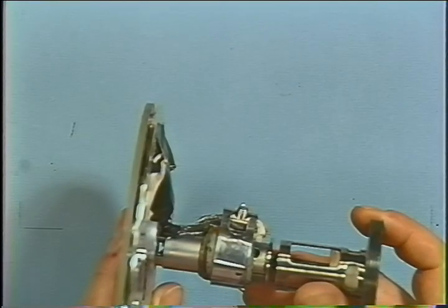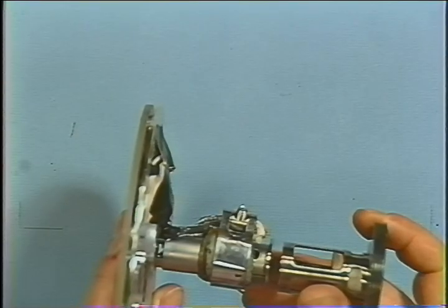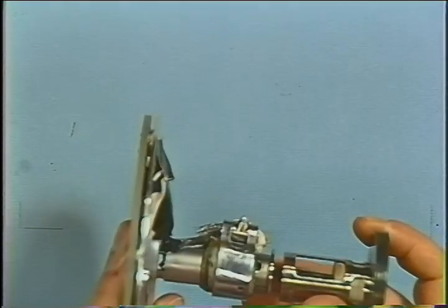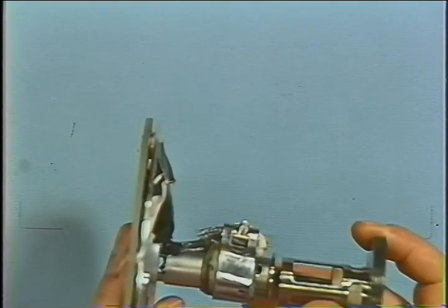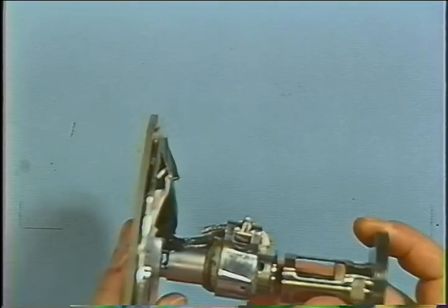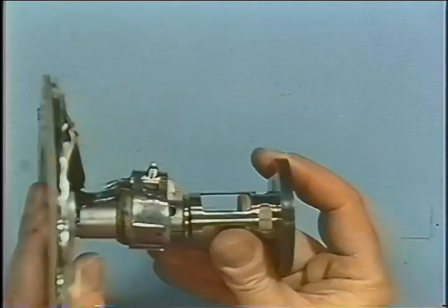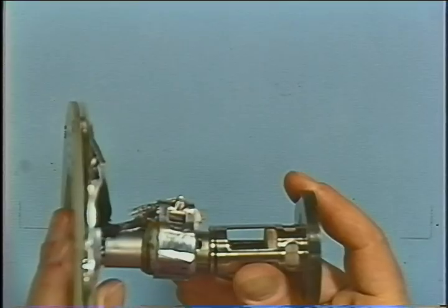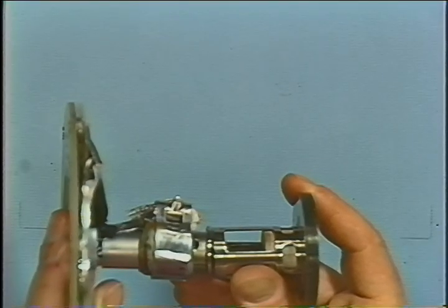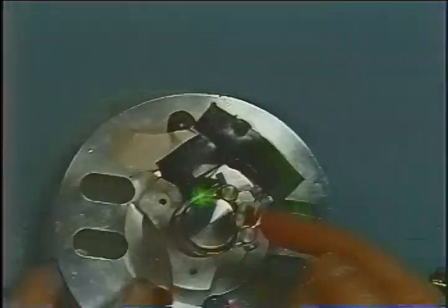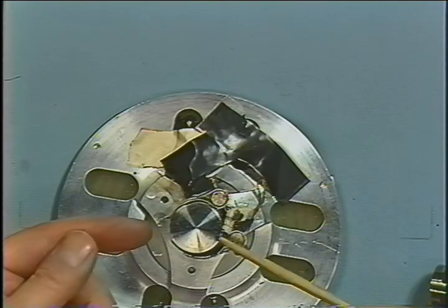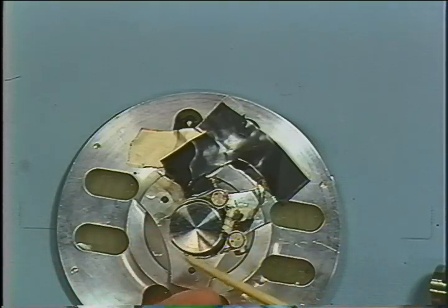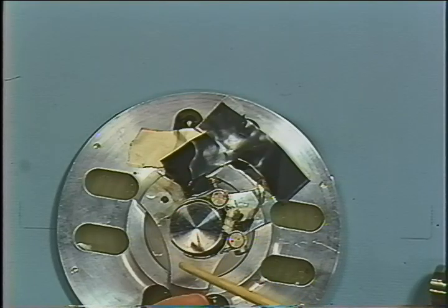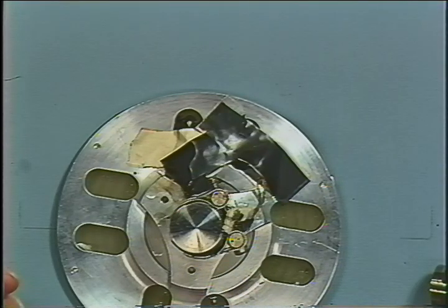And that's why those cone and plate rheometers are really built very stiff to maintain the geometry and the flow conditions for viscoelastic liquids. There are interesting transient artifacts. If you look at this very, very thin gap, and now you have an elastic liquid, and start the flow, which would push this apart, this pushing apart would require liquid to flow to the center to accommodate this new spacing. And that flow is very slow because you're talking about a very small gap setting. So there are all kinds of artifacts.